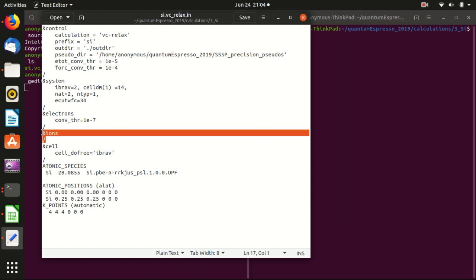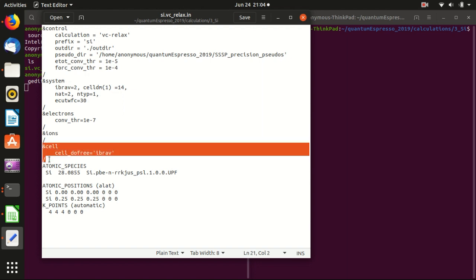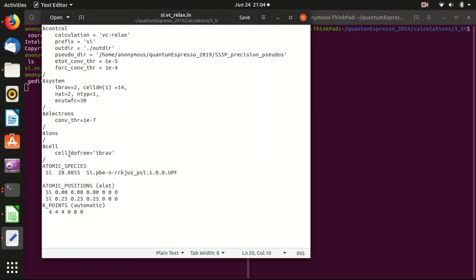The ions namelist specifies the movement of the atoms. Remember, this is only the movement of the atoms, not the unit cell. The movement of the unit cell is specified by this namelist here. The parameter that I want to specify here is called cell_dofree. It means that you tell Quantum ESPRESSO to relax which part or which parameter of the unit cell. If you ignore that, the default setting is that it can relax all the angles and all of the dimensions. So that is not good. We want to keep the shape the same. That's why I specify as ibrav. It means that it basically sets the Bravais lattice to be unchanged.